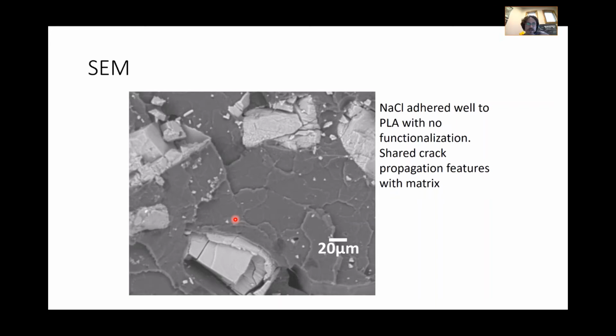Salt started piquing our interest as a research group, and we started looking closer at the micrographs. If we look at this fracture plane, it traverses the interface between the matrix and filler. That tells us there was pretty good interaction between the salt and the PLA. From the point of view of crack propagation, they were the same material, at least in that area. In other areas, salt, which I'd expect to be fairly brittle, kind of cleaved. But it started getting our interest up.